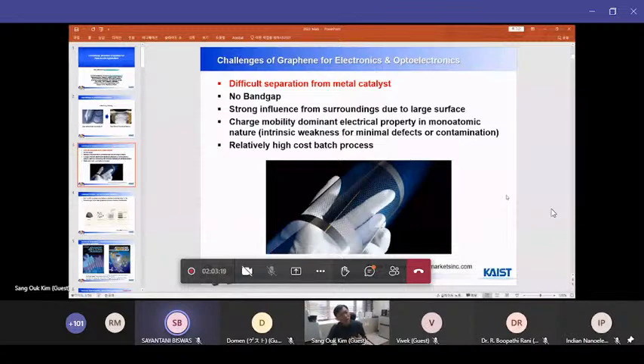So graphene is usually damaged or contaminated during this process. So in the case of graphene, with charge carrier mobility dominating its electrical property, this kind of defect formation or contamination can easily damage the charge mobility. So as a result, the electrical property can be really simply damaged during the post synthetic process. So that's why the idealized electrical properties of graphene are very hard to obtain in the practical real world. So probably in the future, someone can address this issue, but currently industry is suffering from this challenge now.